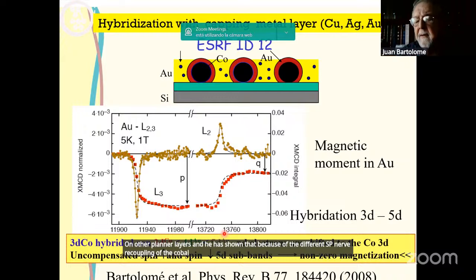But at this interface there is a change in the surface band. It has been studied by Stöhr on other planar layers, and he has shown that because of the different spin orbit coupling of the cobalt and the gold, there is a change in the surface bands with respect to the in-depth bands, and that is why he argues this anisotropy comes from the hybridization between the 3d and 5d. It is also possible if we simply take a thin layer of cobalt and cover it by gold. This has been done by Professor Stöhr before our own work.